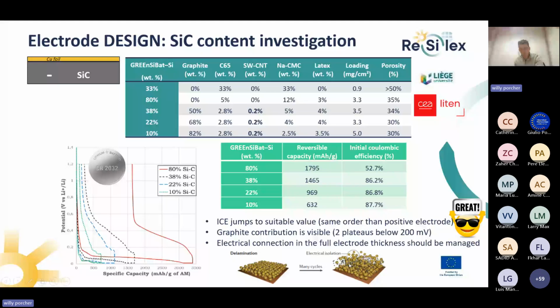You don't have disconnection of particles, and so we are able to shift from 50% of initial Coulombic efficiency to more than 86%, which is quite a nice value already. We also investigated a lower silicon carbon composite, diluting with graphite, so we still have something close to 80% of active material. Still a high reversible capacity compared to graphite with 360 milliamp hours per gram. Here we have much more specific capacity, and a nice initial Coulombic efficiency. So it was a first achievement of Resilex, this formulation development.